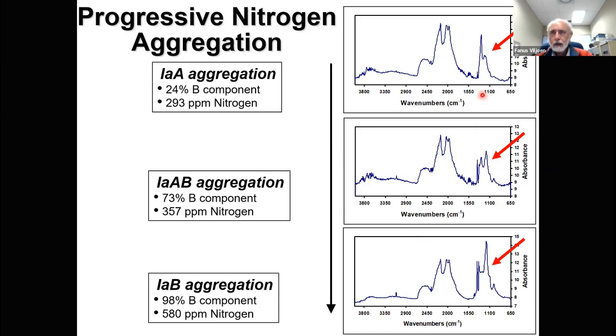The other thing that is quite useful is that you can make a call with regards to how long diamonds have been resident in the lithosphere. For example, some kimberlites have an abundance of diamonds that look like this. And we think that those diamonds have been sitting in the lithosphere for a comparatively short period of time, maybe on the order of hundreds of millions of years, while kimberlites that have an abundance of diamonds that look like this in terms of nitrogen aggregation state probably contain diamonds that are somewhat older than that. But I must emphasize that the errors are huge in infrared spectroscopy. And so to use this as a speedometer in terms of dating diamonds is not particularly successful.